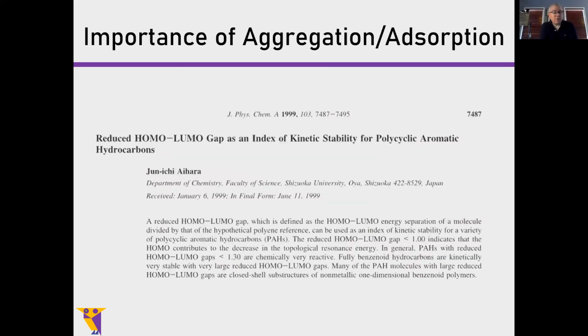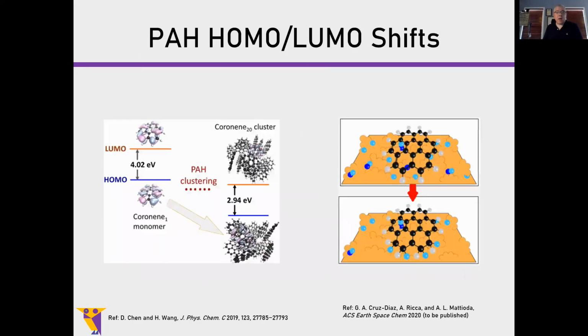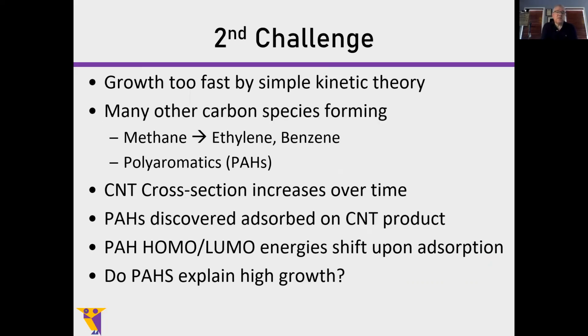And this is why these are important. The HOMO-LUMO gap is basically a ruler for how stable these things are and how they will react and what they will react with. This has been long known. Here's a paper, which is a really nice paper to read. And you will see that as PAHs undergo clustering in the gas phase, you're going to get changes in this HOMO-LUMO gap. And as they adsorb on surfaces, they begin to undergo chemical reactions. So they'll form in the gas, and then they will start aggregating and reacting and forming larger sp2 carbon hexagonal structures.